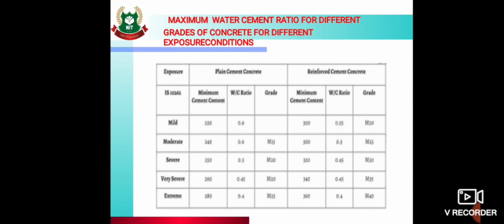Then next is for reinforced cement concrete. For mild condition, minimum cement content is 300 kg per meter cube, water cement ratio 0.55 and grade is M20. Then for moderate condition, minimum cement content is 300, water cement ratio is 0.50, and minimum grade of concrete is M25. Then for severe condition, cement content is 320 kg per meter cube, water cement ratio 0.45, M30. Then for very severe, 340 cement content, water cement ratio 0.45 and minimum grade is M35. Then for extreme condition, minimum cement content 360 kg per meter cube, water cement ratio 0.40 and minimum grade is M40.